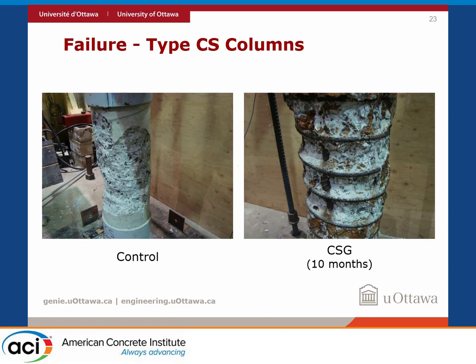This is the case where the spirals were corroded. So we have here the control one. We had a typical failure with concrete spalling at reaching the first peak, but it was able to sustain the second peak, keeping confinement. And the other columns were also able to attain the second peak, with confinement maintained. We believe it had to do with the fact that the longitudinal reinforcement was not corroded and also provided some confinement to the column.